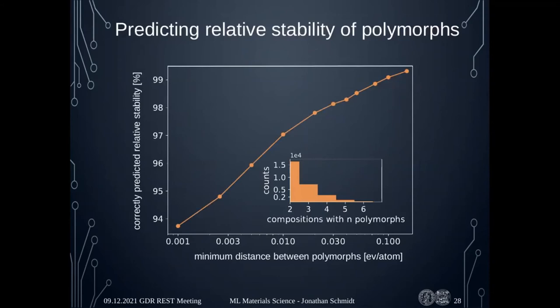We also considered predicting the relative stability of polymorphs — checking whether our model, despite imprecise crystal structure information, can accurately predict the relative stability of compounds with the same composition but different structure. This worked quite well: once we only consider polymorphs that are at least 100 meV apart from each other, we can get most of them correct.